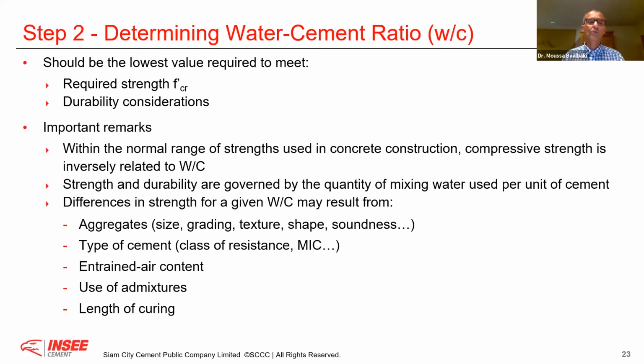Okay, and why are we sticking to the 28 days? Because we are used to working with OPC. When a lot of technology was developed with concrete, it was the time of OPC, and we know OPC develops at 28 days almost more than 80 to 90% of the strengths. But if you take, for example, a composite cement, what we call blended cement, those blended cements continue to develop their strengths up to 1 year. If you look at the 56 days, the 90 days, of a concrete produced with blended cement, or Portland limestone cement as a ternary system, you see the strengths continue to gain with time. And in the case of OPC, it will be flattened because you have developed the maximum of the potential coming from the clinker. Therefore, you have to take this also into consideration.